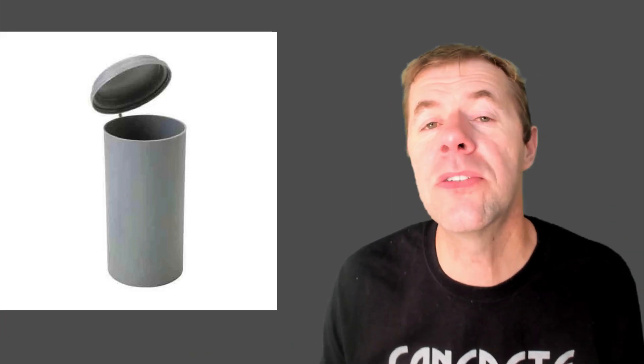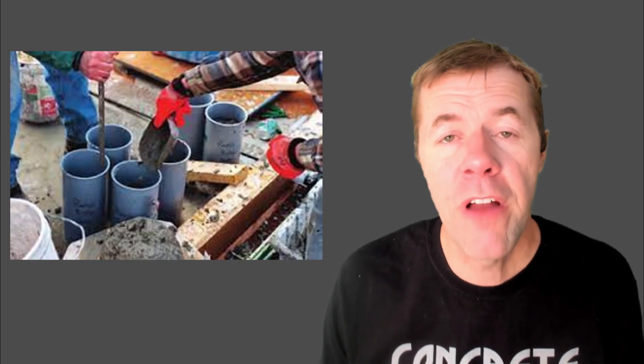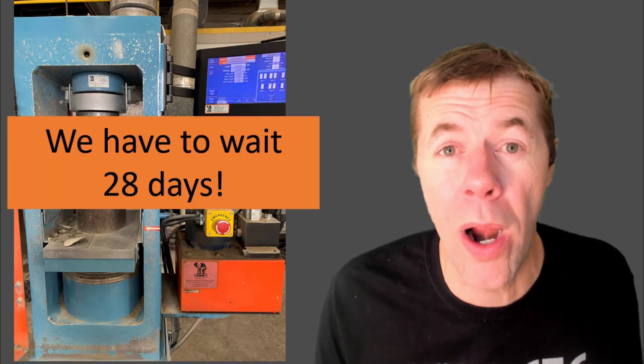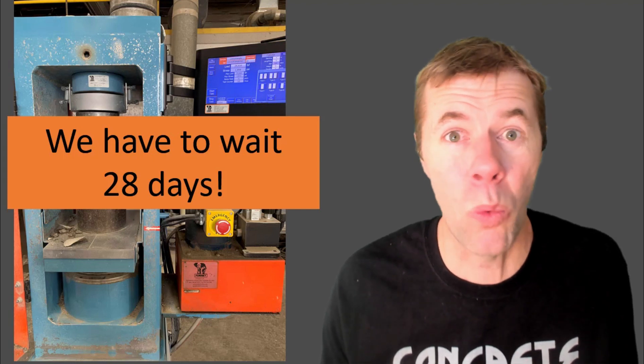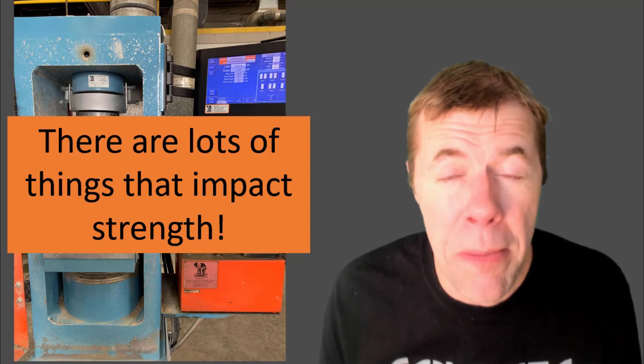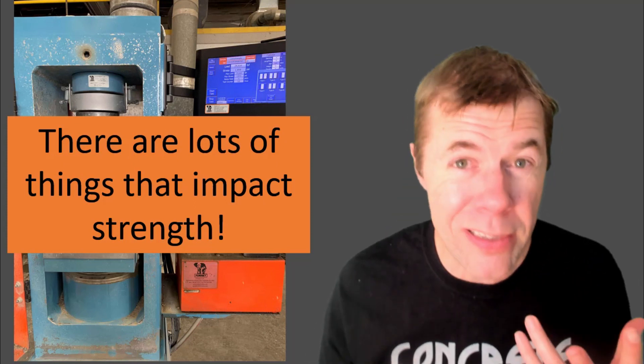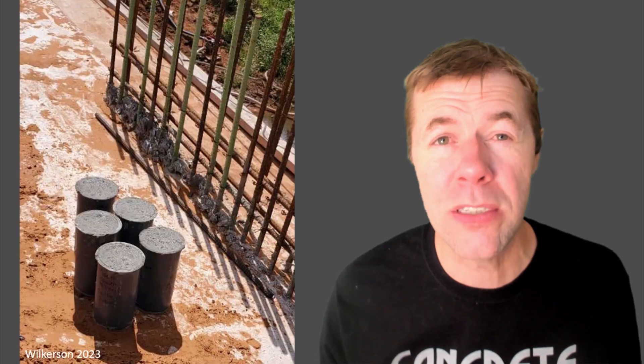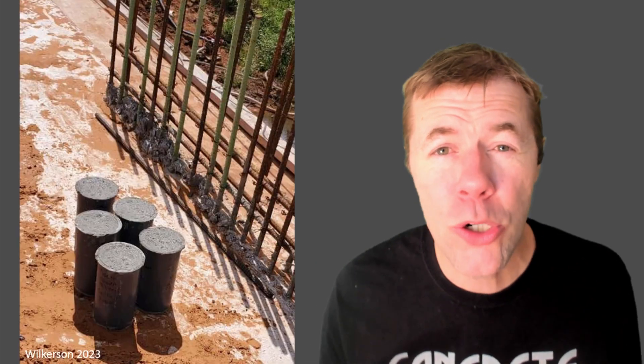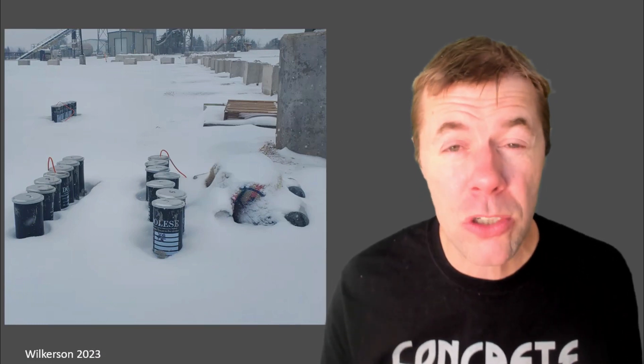What else is there? Some people do these things called strength tests, where they make cylinders, where they fill them up in a consistent manner. There they are dumping them in. They strike them off. They let them harden. They demold them like this. Then they break them in a machine like this. But we have to wait 28 days. At least most specifications require 28 days before they will say whether that concrete is good or not. So you have to just sit around and wait the entire time in between to see and wonder, is it right or is it not? There are lots and lots of things that impact strength. Water is one of them, but there are so many more. And the biggest thing that impacts strength is how these cylinders are handled, right? How they're treated. Like this. You don't want this. They just throw them on the ground. You think that's going to be good for your concrete cylinders? What if we just leave them out without a cap on? Drives me crazy. Or we leave them out in the snow? Do you think that's going to affect the strength? Sure it does.